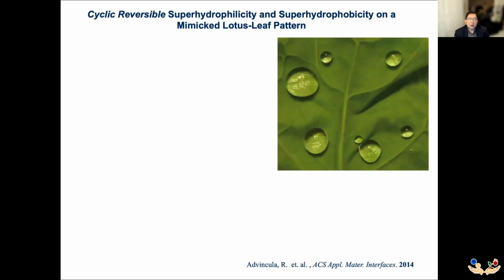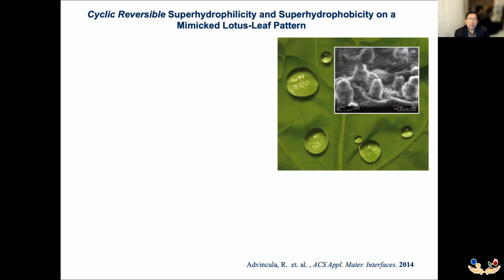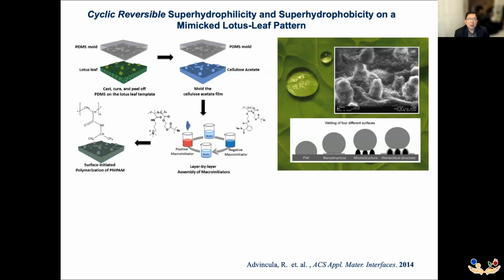One of the interesting things we did was to mimic the structure of the lotus leaf pattern in order to produce artificially superhydrophobic films that are bio-inspired. So in this case, we use molding or in particular a PDMS stamp where we grow polymers based on ATRP initiators. In this case, we grew a polymer that is based on polyNIPAM or poly N-isopropyl acrylamide, which has an LCST behavior around 32 degrees C.